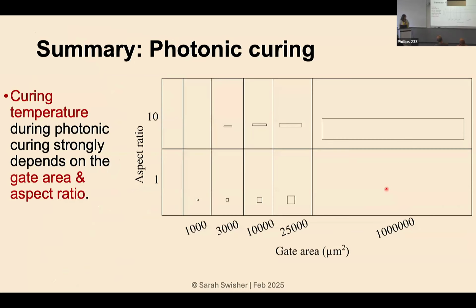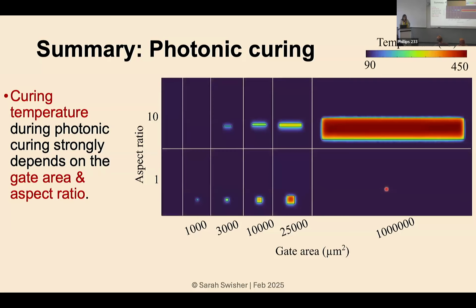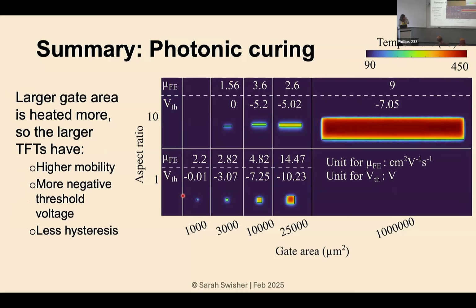So the summary that we took away from this work is that the curing temperature during the photonic curing really strongly depends on both the area and the aspect ratio of the gates. So you can see here, the color is representing the peak curing temperature. For these different devices, you're reaching very different temperatures, and that's going to have a huge impact on the device performance. So we can see the variation in the mobility going from only about 2 to a mobility of about 15 for some of these larger devices.